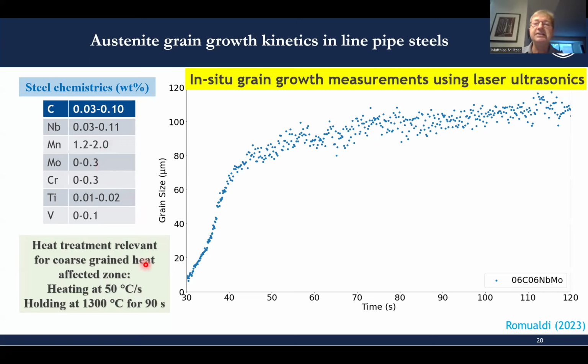And we do a classical heat treatment study, heating at 50 degrees per second to a holding temperature of 1300 degrees, where we kept for 90 seconds. And it kind of replicated what we would maybe assume to be happening when we go very close to the melting temperature, where the peak time, holding time, if you want, is maybe a second or so. And we see initial rapid grain growth, and then we see that we get into a limiting grain size.